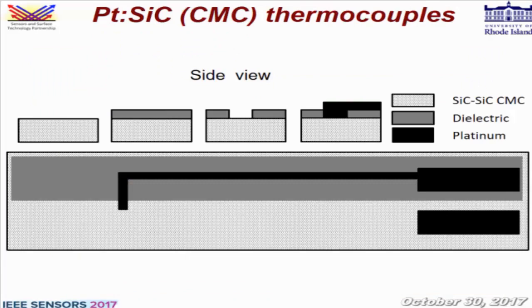So this is just a schematic of how to make one of these and just a rough view of what they look like. We start off with a bare CMC substrate, coat it with a dielectric, heat treat the dielectric, and then the third step, which is the most important, we make a hole in the dielectric where we want the platinum to make contact with the CMC material, because the CMC is one conductive part of the thermocouple and the platinum will be the other. And where they meet is where the voltage will be produced. So this area here is where the voltage is produced, and it's roughly in this region here.